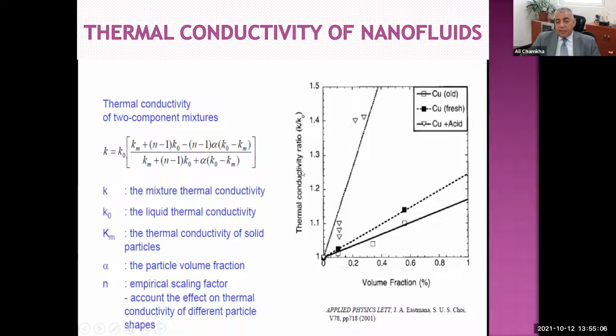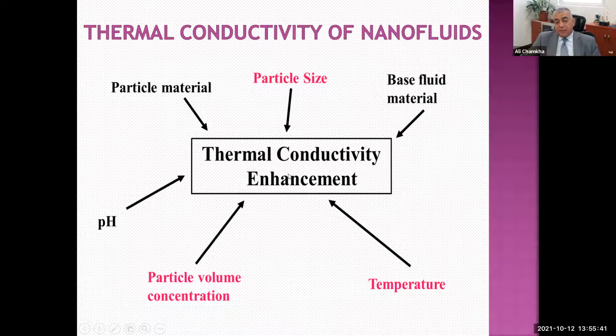If you look at this curve, thermal conductivity versus volume fraction, the amount of nanoparticles being added to the fluid, you can see this is for copper, for example. The solid one is old copper. This is the copper plus, this is fresh copper. And this is when you add a little acid, you will see a tremendous increase in the thermal conductivity as you increase the volume fraction. This is based on a two-component mixture calculation, the theoretical calculation, but in experimental calculations, you have slightly different results.